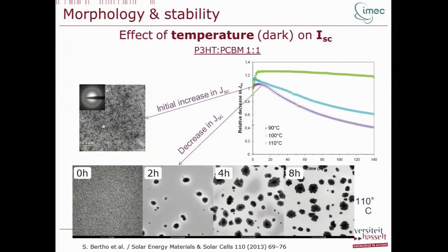So what happens at high temperatures is that here is, after 2 hours, a TEM picture of a film submitted to 110 degrees Celsius. This is for P3HT:PCBM. After 4 hours, after 8 hours, you see how your nice, ideal nanomorphology evolves towards these kinds of chunks. And what are these chunks? This is the PCBM that comes together. So you can also imagine if your morphology changes, that also your current is changing, and this is what we see here, measured at our extreme conditions, 90 degrees Celsius, 100 and 110 degrees Celsius.